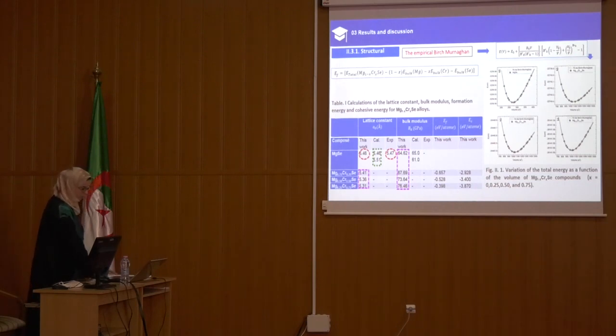To justify the existence of our compound MgSe doped with chromium at different concentrations in the rock salt ferromagnetic structure, we computed the defect formation energy and the cohesive energy. We found that both the formation energy and the cohesive energy have negative signs. These results indicate the stability of our compounds in the rock salt structure, which suggests that this system can exist in the rock salt phase.